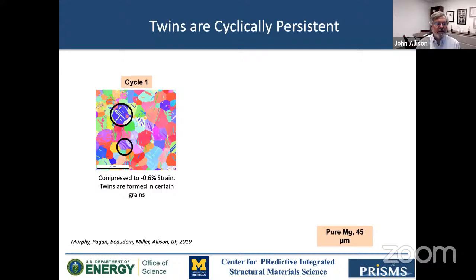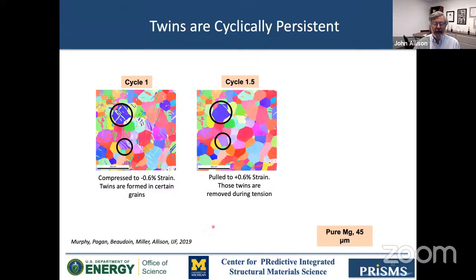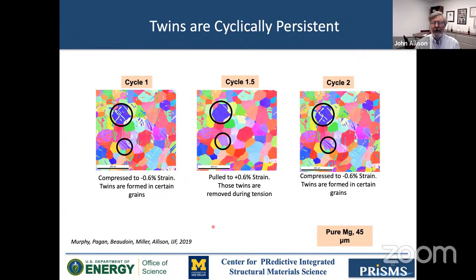So she compressed this, then unloaded it and saw the twins. Then she loaded it in tension, looked at it again at zero load, and saw the twins had disappeared. Then she loaded it in compression and unloaded and saw the twins in almost exactly the same location. There are a few additional ones here, but pretty much in the same location. So this twinning is persistent cyclically.